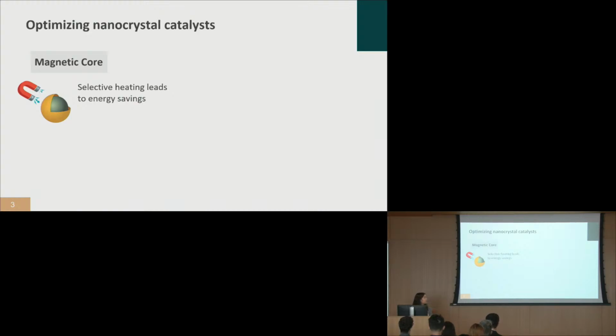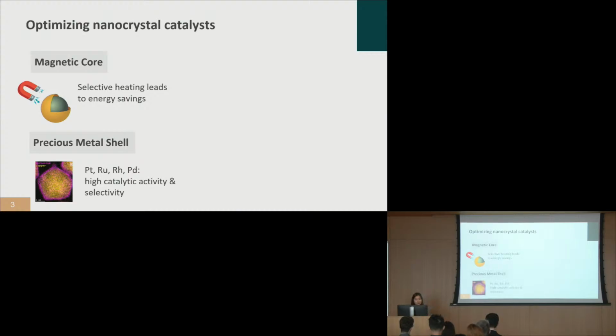So we can heat nanoparticles selectively by applying a magnetic field around a whole system, and that minimizes energy loss to the surroundings. However, the elements that we use for this, like iron and nickel, are not great catalysts. So that's why we need to use a precious metal shell for the surface chemistry.